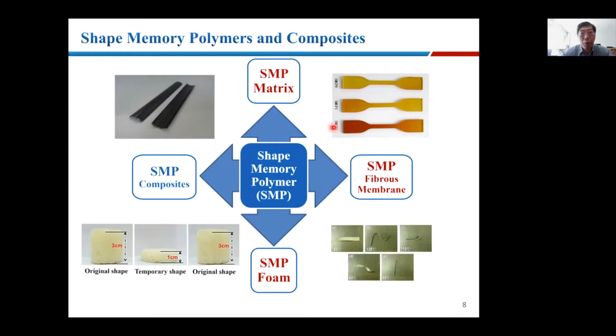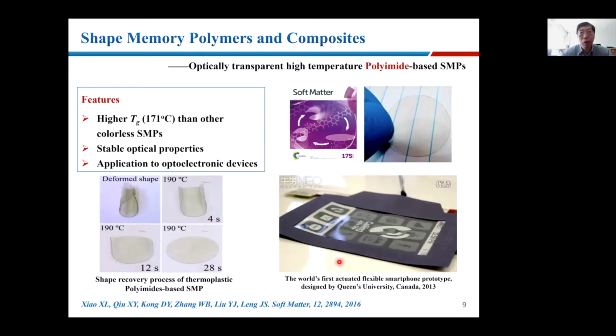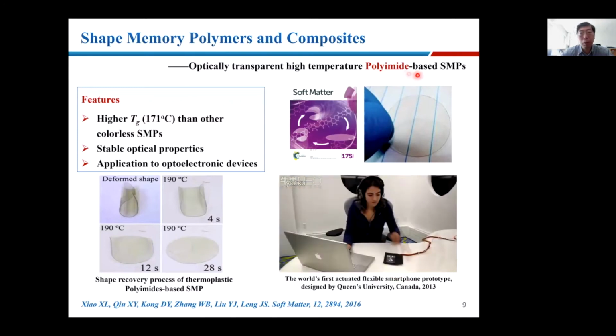So if you have a shape memory polymer like this one, you can do different things. So you can make a composite, and also you can make a foam. The foam can change in shape by heating at a different temperature. Also, you can do electrospinning to make a membrane. With this one, with different temperatures, they can remember 5 shapes, like 160 degrees, 135, 110, 90, and 65.